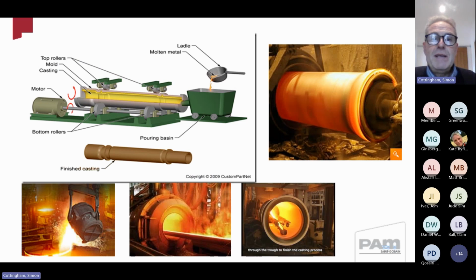Manufacturing pipes, we melt the ductile iron to about 1500 degrees centigrade. We put it in a hopper. Here at the end we have a pipe mould spinning and the molten metal is poured into the spinning mould, and the pipe is cast using a centrifugal process. Here you can see a large diameter pipe still spinning, being pulled out of the mould. So that's how we make pipes, and that's why pipes are always a set length.